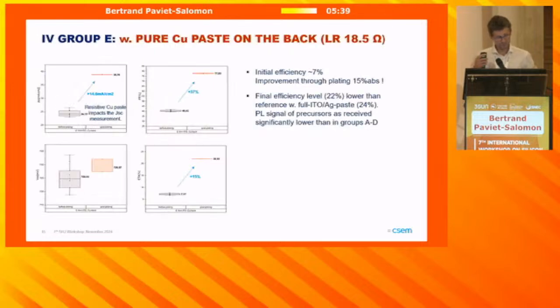I promised to also give an explanation on this group E samples featuring pure copper paste on the back. As I said, in the as-received state, they feature very low fill factor because this copper grid on the back is not suitable for good transport. But after plating, the fill factor is pushed much higher, close to 78% in that case.